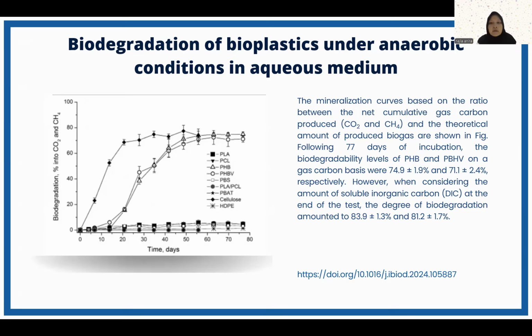Following 77 days of incubation, the biodegradability levels of PHB and PHBV on a gas carbon basis were, for PHB, 74.9 plus minus 1.9%, and for PHBV 71.1 plus minus 2.4% respectively. However, when considering the amount of soluble inorganic carbon, or DIC, at the end of the test, the degree of biodegradation amounts to be 83.9 plus minus 1.3%, and 81.2 plus minus 1.7%.